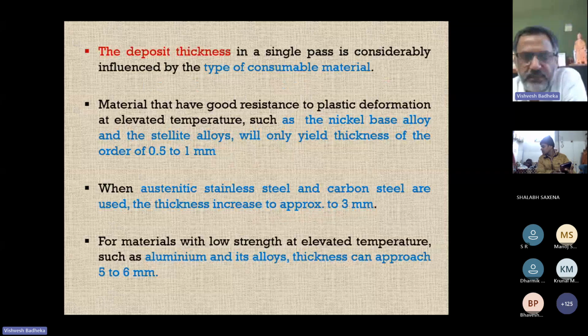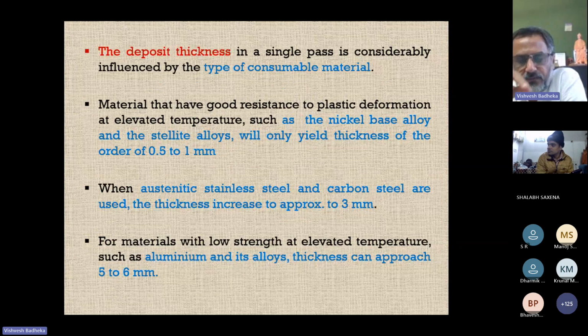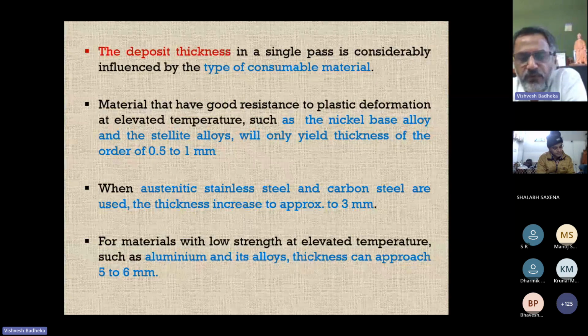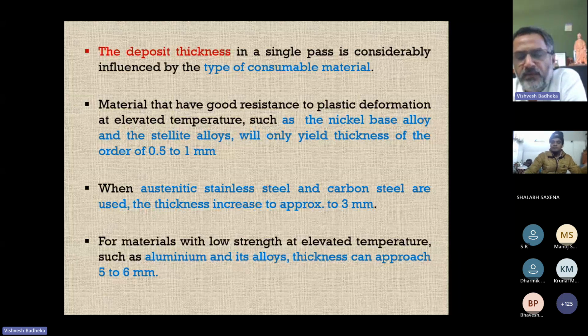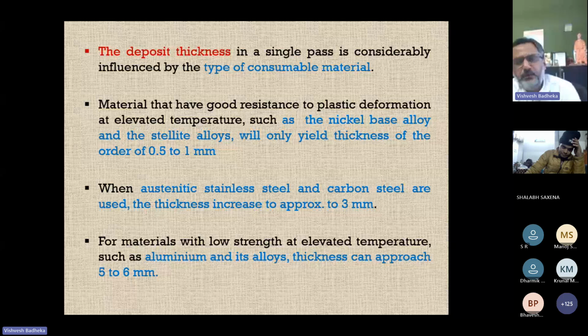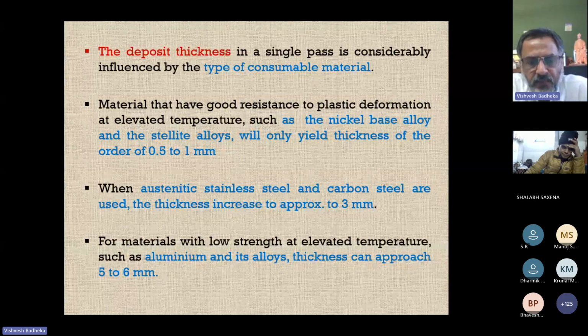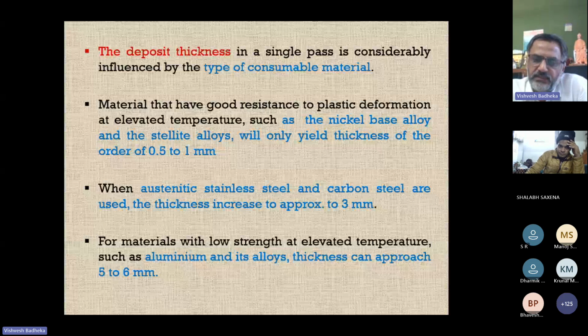And the material which you are depositing, say for example aluminum, is very soft, and magnesium is very soft. In one go, the thickness you are achieving may be close to 5 to 6 millimeter. But as you move on to high strength material like steel and stainless steel, the thickness you are getting in one pass may be close to 3 millimeter. In case of further high strength materials, like nickel based alloy and stellite alloys, the thickness in one go may be close to 0.5 to 1 millimeter. So please understand, different materials have different strength and different melting point, and soft material deforms more, so the thickness you are achieving in one go may be of higher order, 5 to 6 millimeter. As you approach the high strength and high melting point material, the thickness you are achieving in one go may further go down.